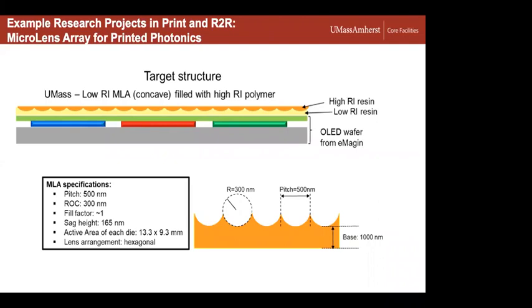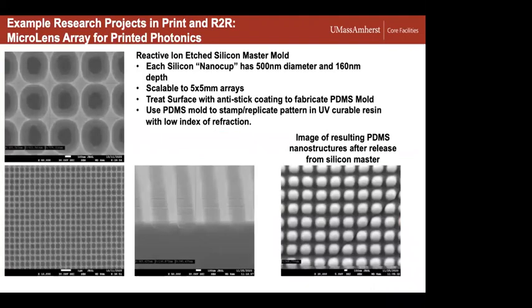We used specific processes to etch these patterns, forming a master mold from which we created a daughter mold. Then we're able to stamp these patterns into a resin having a specific dielectric constant or refractive index, so that they could get the particular photonic and optical properties they were looking for. This is an example where we pattern these using e-beam lithography. We etch these in silicon using reactive ion etching. And then on the lower right, we created a PDMS daughter mold from that, which eventually is our stamp to create these patterns in the refractive index material of interest.